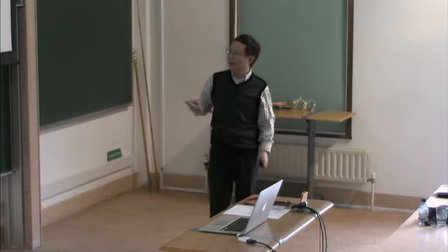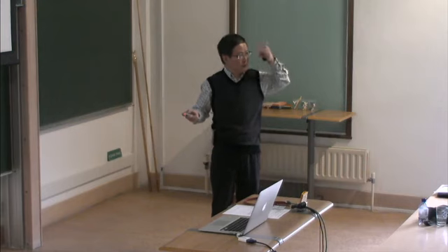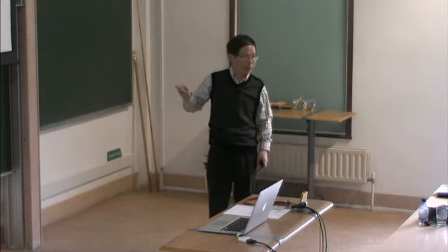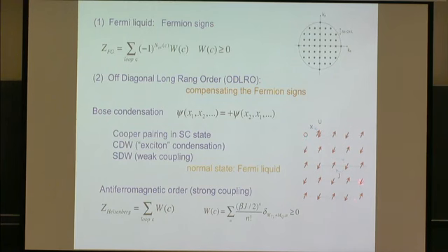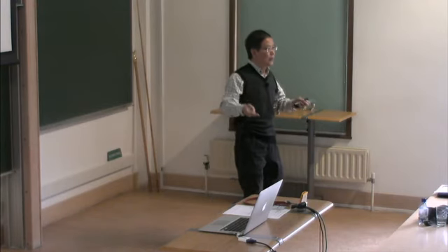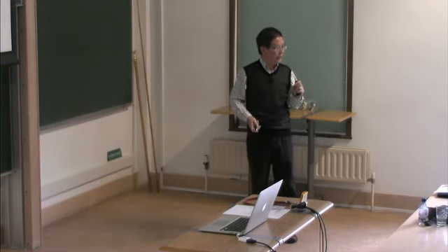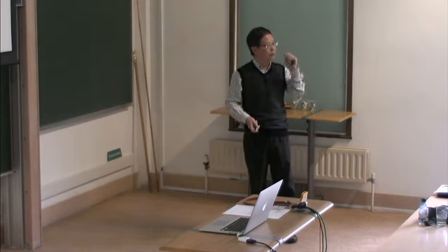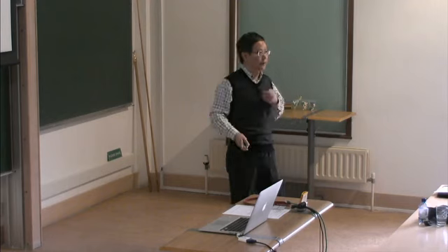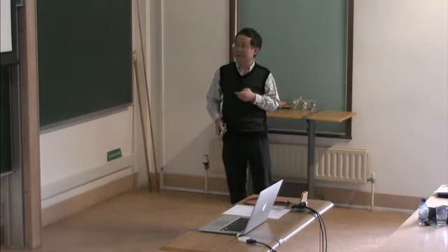But if you imagine increasing the temperature to melt the long-range order, then at high temperature you still see that this system is different from a Fermi liquid, because there's no fermion sign at all. So this is the simplest extreme case, where it tells you the interaction will totally change the nature of the system by changing fermion signs.